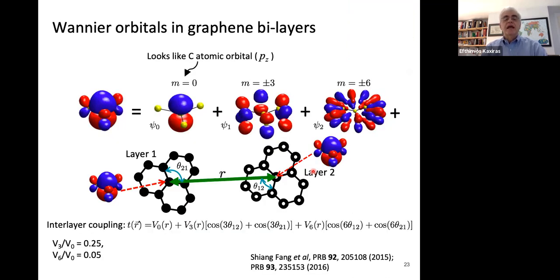And just to give you a glimpse of what these states look like, these are the Wannier orbitals for bilayer graphene, and they can be decomposed into states of different angular momentum. The zero angular momentum state looks like the pz orbital, the atomic carbon orbital, which is often taken as the basis. So the basis is actually quite a bit more elaborate in its behavior, in its angular dependence. So putting these kinds of orbitals at every point in the graphene lattice of layer one and every point in the graphene lattice of layer two and allowing for all these interactions gives us a good handle of the electronic states that result from this bilayer system.